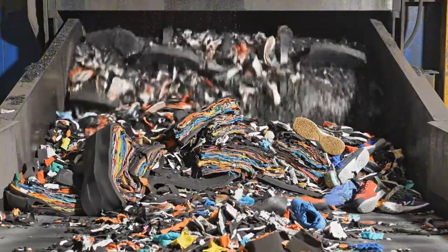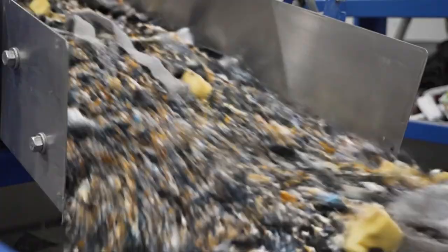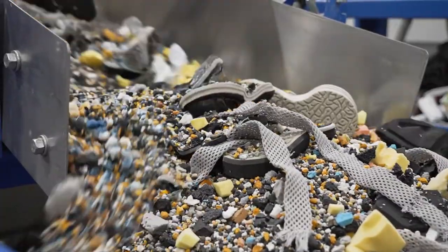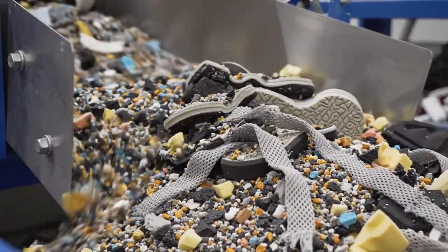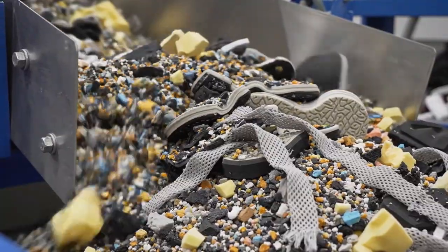The shredder does not simply tear the shoes apart. It subjects them to shear forces exceeding 20,000 pounds per square inch, forces sufficient to overcome the molecular bonds in vulcanized rubber and rip through the laminated layers of modern performance footwear. What emerges from the discharge chute is barely recognizable as footwear.